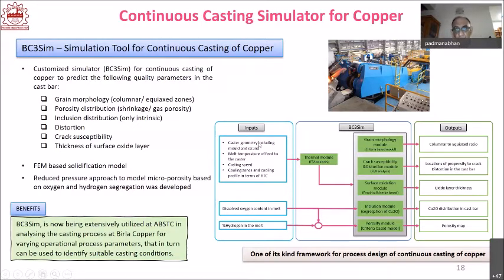And therefore, you have a thermal model taking all these into account. There, you will be able to predict the grain morphology, that is the columnar to equiax transition, and crack susceptibility, that is, you find out the points where the stress concentration is the highest, and there the crack susceptibility would be the highest. And then distortion, which can come out of solidification shrinkage, and also thermal gradients, which will also introduce residual stresses. By a proper analysis based on finite element, you will be able to identify the locations which are likely to crack, and also where distortion is likely to be maximum.